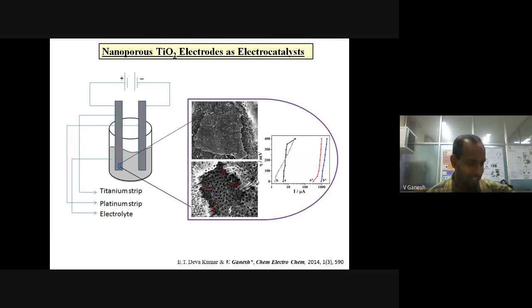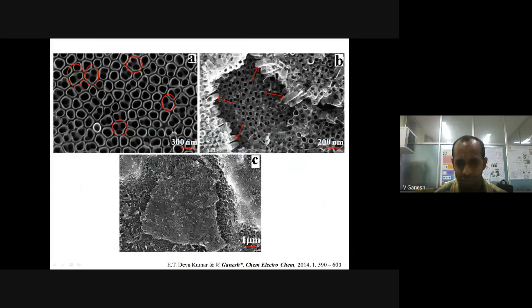Now, maybe I will describe only one work and I will wind up my talk. Okay. So though we developed many different catalytic materials for this reaction, I would like to highlight a very, very simple method, right? You do an electrolysis, you use an anode and cathode, you do a water electrolysis. What we did here is we used a titanium substrate as an anode and platinum as a cathode. And when you anodize this titanium, by playing with the composition of the electrolyte and the current density, one can tune the resultant output, as you can see, a beautiful honeycomb-like structure of TiO2 nanotubes.